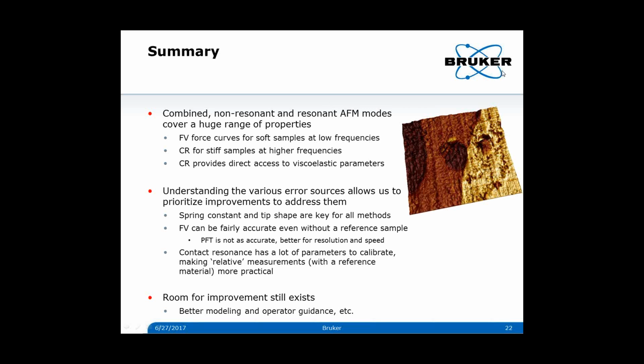Well, peak force tapping, that sinusoidal Z motion is a little harder to get an accurate measurement on than the linear measurement that's done in force volume. Basically, in peak force tapping, you need to both measure the amplitude and the phase of that sinusoid, and a very small phase shift can cause an increase in error, so essentially it will be a little bit less accurate just due to that. Hopefully that answers the question.